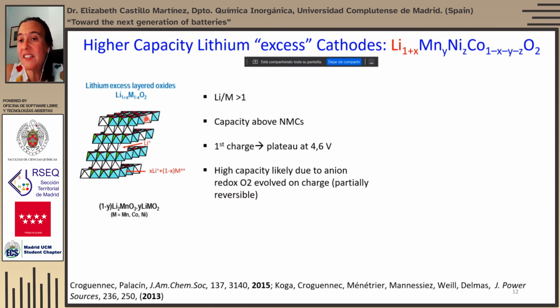Surprisingly enough, this gives capacities which are above the capacities of the NMC compositions, and also a very large plateau on the first charge at about 4.6 volts versus lithium. And there is a lot of discussion about this, and it seems that the most agreed argument is that the high capacity is likely due to anion redox on the oxygen sublattice. But this is an issue because the oxygen can evolve. And although in the bulk of the particle the oxygen is not released, it just reacts kind of reversibly,